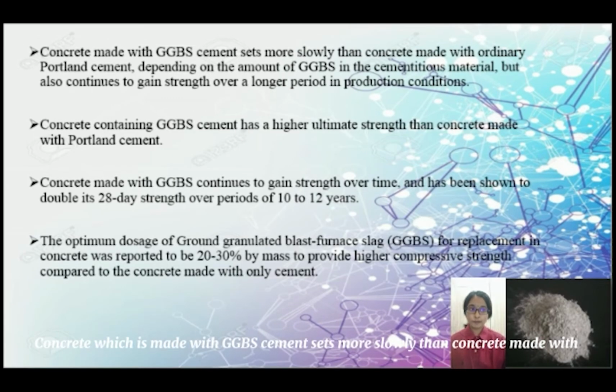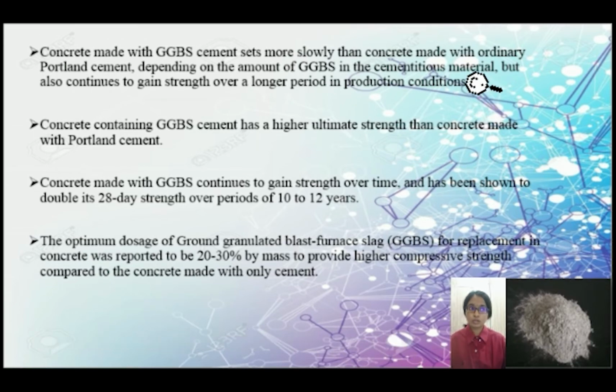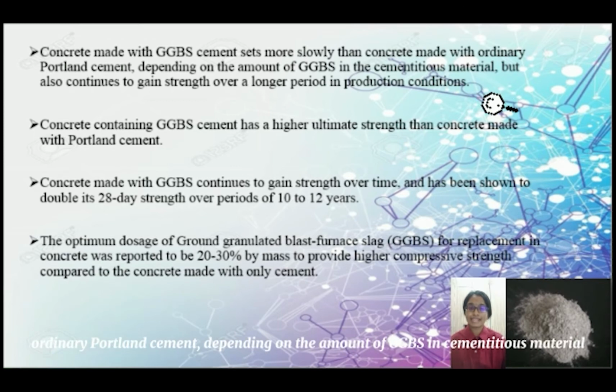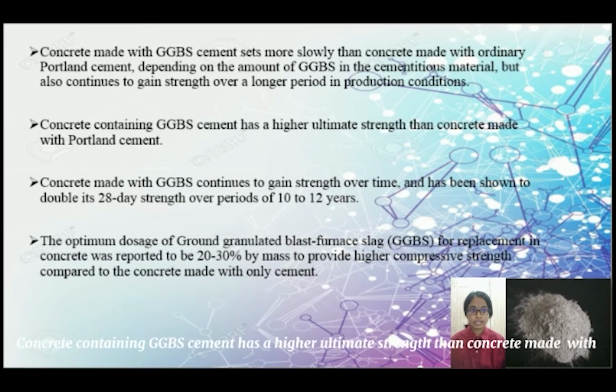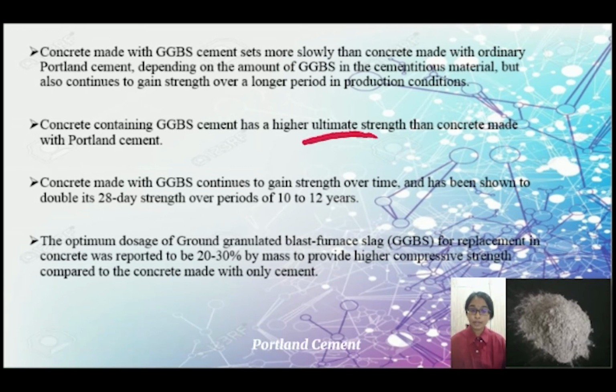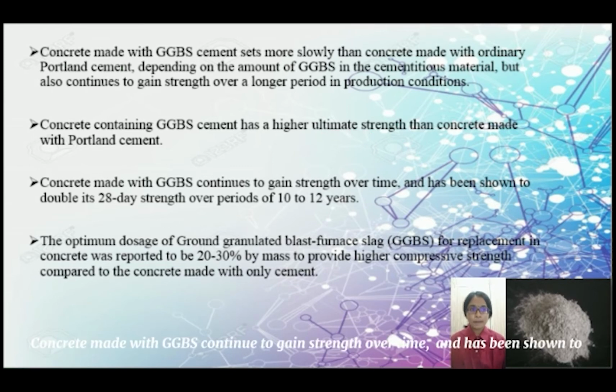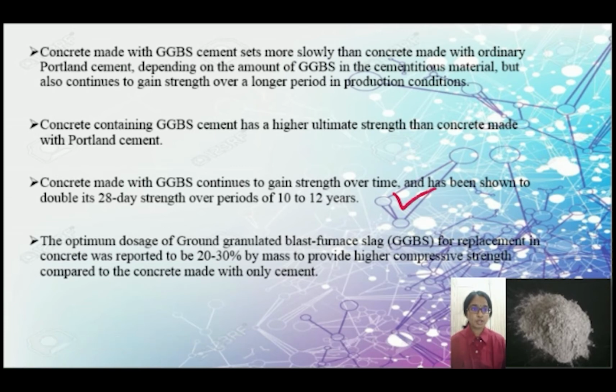Concrete made from GGBS cement sets more slowly than concrete made with ordinary Portland cement, depending on the amount of GGBS in the cementitious material, but also continues to gain strength over a longer period in production conditions. Concrete containing ground granulated blast furnace slag cement has a higher ultimate strength than concrete made with Portland cement. Concrete made with GGBS continues to gain strength over time and has been shown to double its 28-day strength over periods of 10 to 12 years.